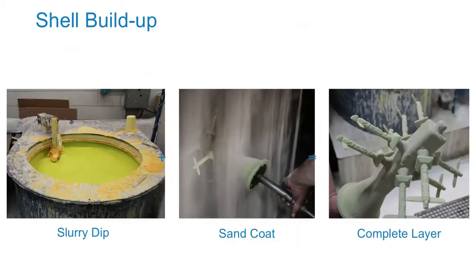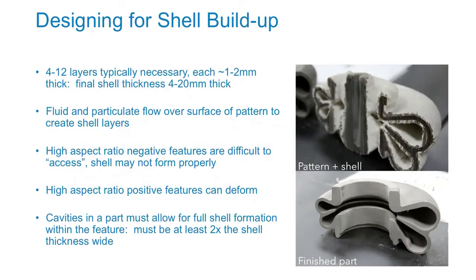So again, the shell buildup consists of that slurry dip and then that sand coat to build up that complete layer. We generally go through between 4 and a dozen layers. What you want to think about here is we've got 2 mechanisms. We've got a fluid flow challenge of getting that liquid ceramic slurry to coat every surface evenly to correctly build up that mold wall. It's important to think about, what we're doing here is constructing that mold. So we're building up the mold, and you want both components, the sand and the slurry coat, to have access to that part.